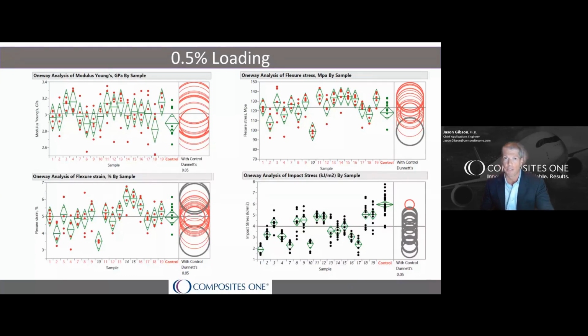Now let's also look at the toughness results in the bottom right graph. Here you'll see that all the samples showed significant change in the toughness, but in the wrong direction. All of them lower the toughness of the base resin. So in summary, none of these results from 0.5% loading are promising.